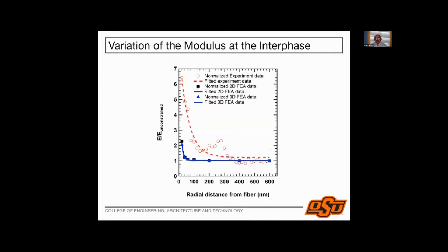So what we find is that there is a constraint effect. Yes, there is a constraint effect, but the constraint effect does not come into play until I'm very close to the fiber. So this x-axis is the distance from the fiber. And the constraint effect is much smaller than the experimentally observed increase in elastic modulus. So we are actually seeing an increase in elastic modulus in the interphase region. The width of the interphase is about 150 nanometers. And the amount of increase that you see in the elastic modulus is at least 3 or 4 times the rest of the matrix. Now the problem is that if you're seeing this, this means what?